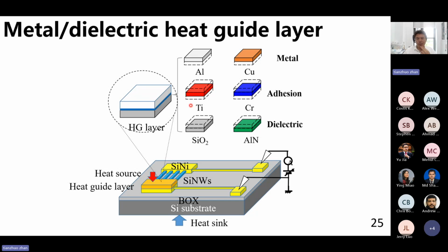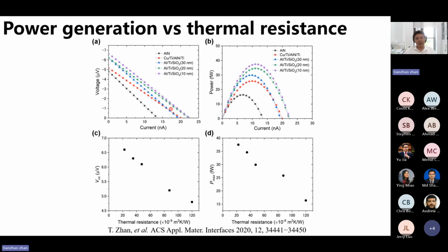And so to improve the adhesion between the metal layer and the dielectric layer, we use different combinations of these layers to form different heat guide layers, and we measure the power generation of all these TEGs, and we found the open circuit voltage and also the power density increased with decreasing thermal resistance of the heat guide layer.